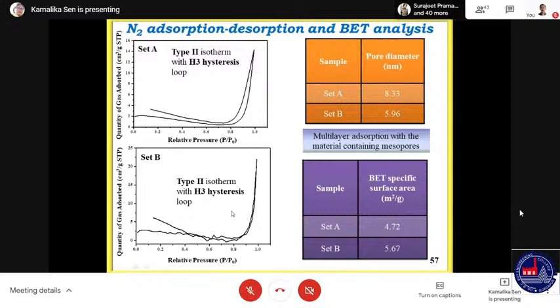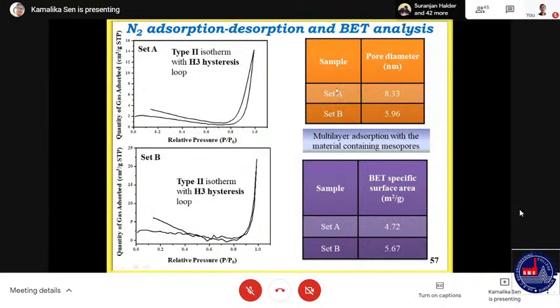Now with the particles, we have tried to see what is the pore diameter. We can see with set A, that is with non-irradiated sample, the pore diameter is higher. With set B, that is with the irradiated solution, pore diameter is less. But the BET surface area, the total surface area is however a little less for set A and little more for set B. This is because of the lesser particle size of the irradiated nanoparticles.